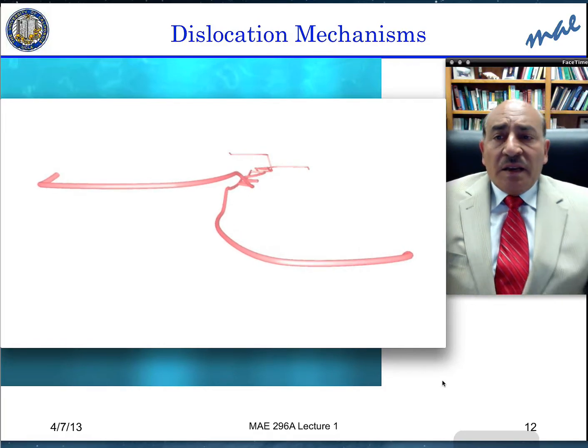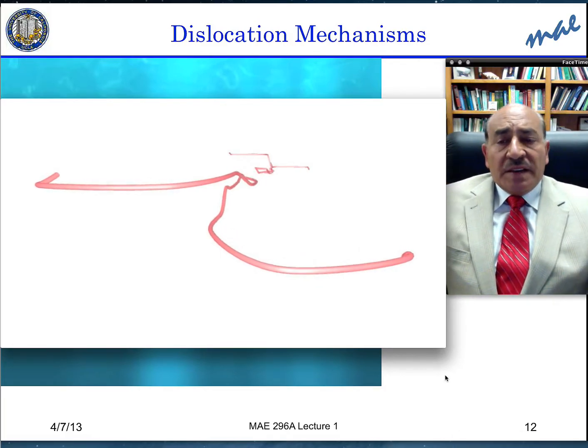Here you can see mechanisms where you have cross slip of the dislocations forming a dislocation loop, called a dipolar loop. You can see it's struggling, cross slip, and the dipolar loop forms and continues on. Cross slip by screw dislocations is a very common process in materials and produces many of these dipolar loops that you will see in this movie.